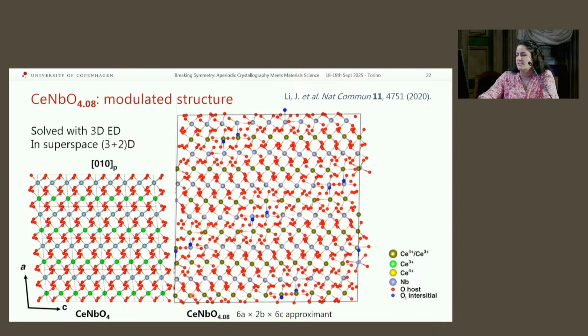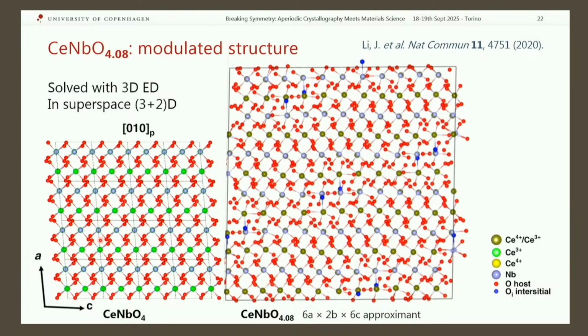So they solved the incommensurately modulated structure, which, again, by seeing it over multiple unit cells, we can compare it with the average stoichiometric compound. So you see, first of all, the presence or not of this oxygen atom in blue, the interstitial oxygen atoms. And again, we see that all the other atoms have to accommodate for them.